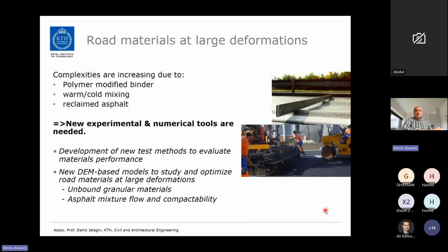This problem is also quite complicated. Even for standard road materials, we have a lot of parameters affecting large deformation performance of our material, be it the aggregate size distribution, binder content, temperature, load level and load configuration, and 3D as well. And those complexities are only increasing when we move to new types of materials: polymer modified binders, warm and cold mixes, workability additives, reclaimed asphalt, and so on. Those things just become more and more complicated, and it becomes problematic to rely on empirical evidence available for the standard materials. And this means that we need new experimental and numerical tools to describe material behavior in those situations, and preferably to describe it from a fundamental mechanical point of view.